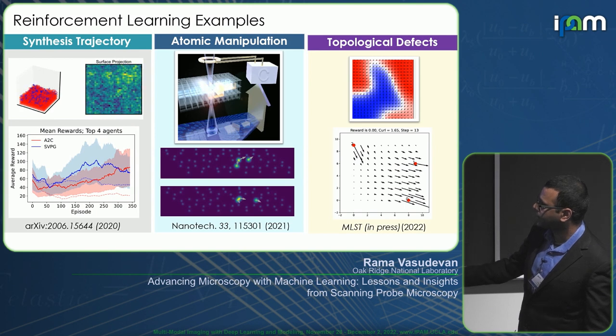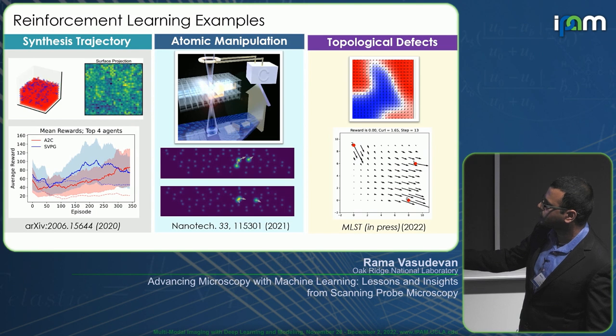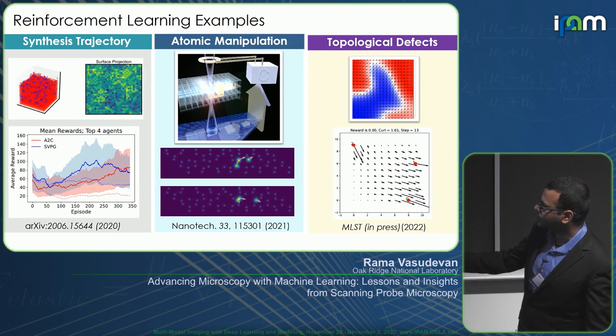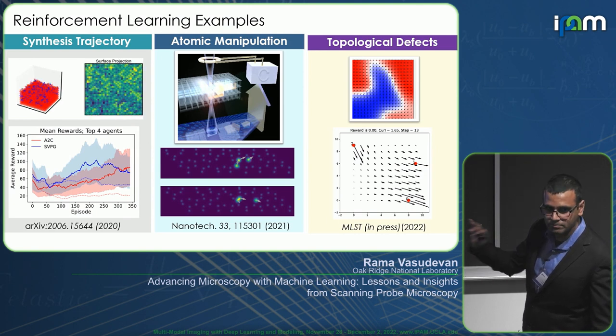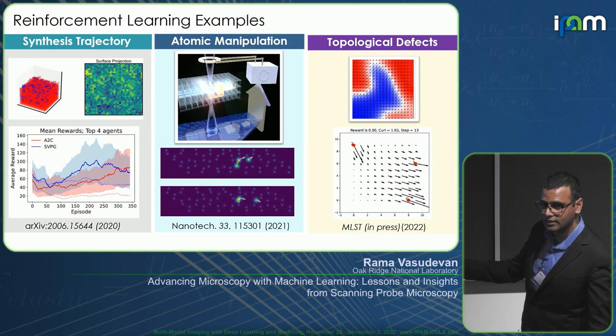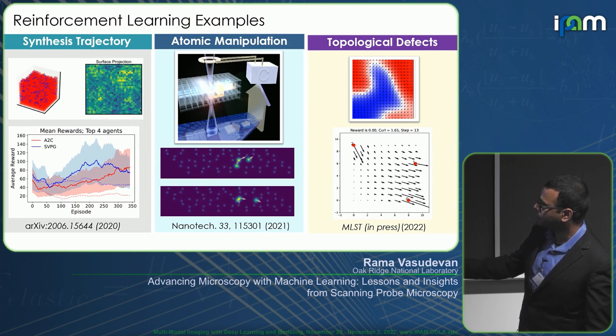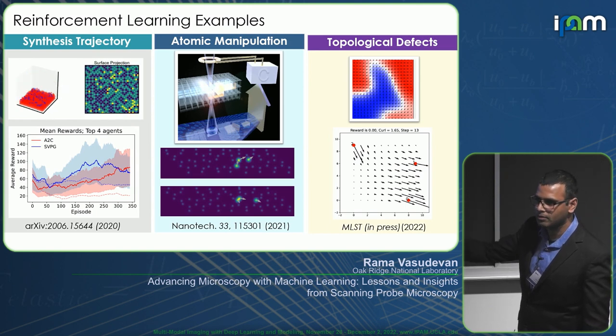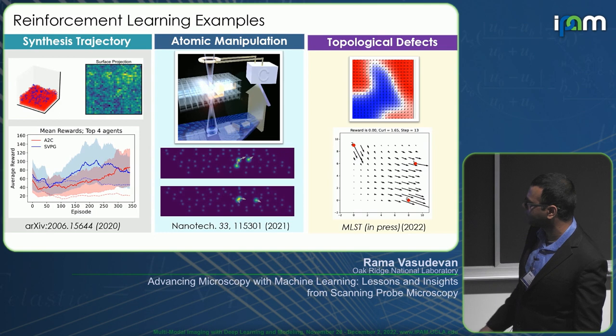We can also do things like atomic manipulation. So here, these are molecular dynamics simulations where we want to, for example, use an electron beam to adjust the momentum that's being transferred to dopants, in this case, silicon dopants in graphene. But this is just a molecular dynamics simulation. It's a very simple version of what we would actually see in an electron microscope. The point is that we can run this RL algorithm in this simplified space to give us some insights into how we would control dopants in this particular system by imparting momentum on these through the electron beam.